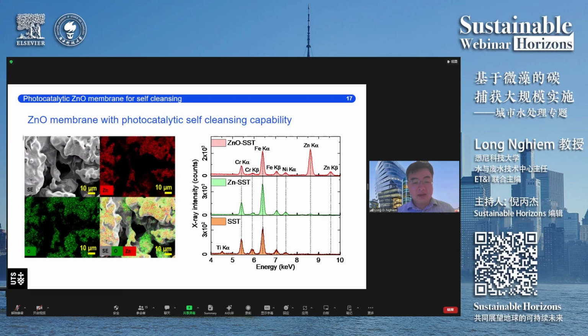So this diagram shows us the elemental composition of the membrane surface after we have coated it with zinc oxide, and it's very evident here that we see zinc all over the place, which is good. With zinc oxide coating, I mentioned before that we have a slightly thicker layer, and therefore the peak is stronger compared to the case when we coat it with zinc and then oxidize into zinc oxide. And when we look at the substrate, which is stainless steel, we only see the material in stainless steel, which is nickel and iron.